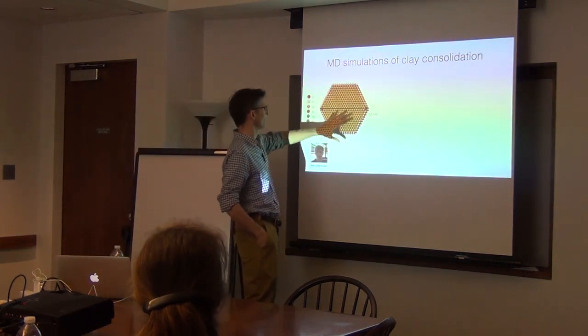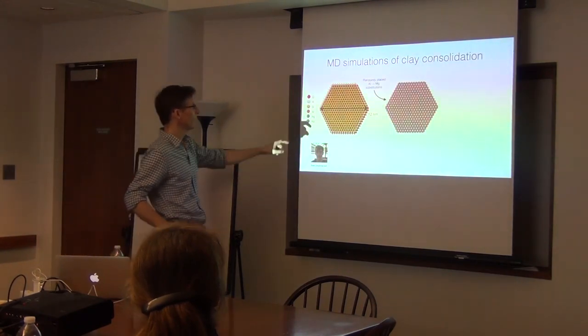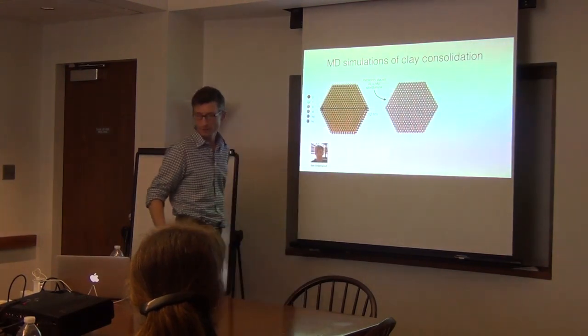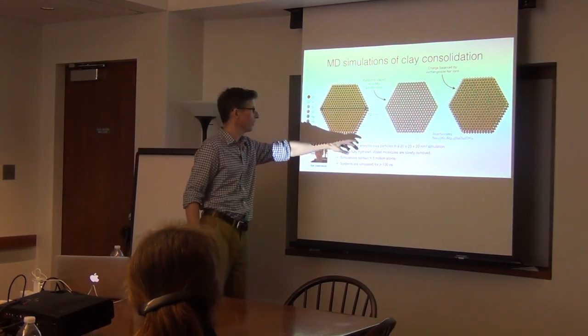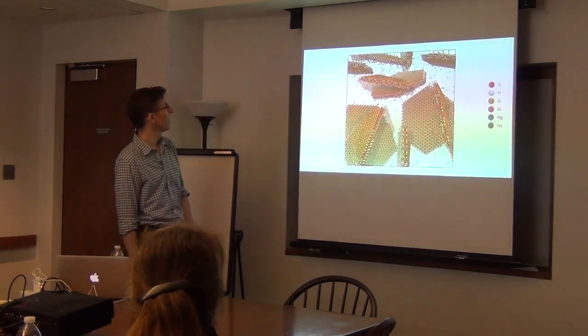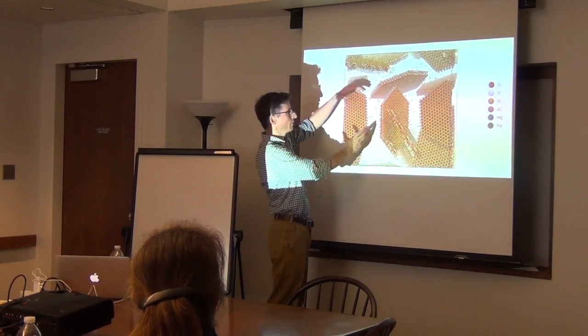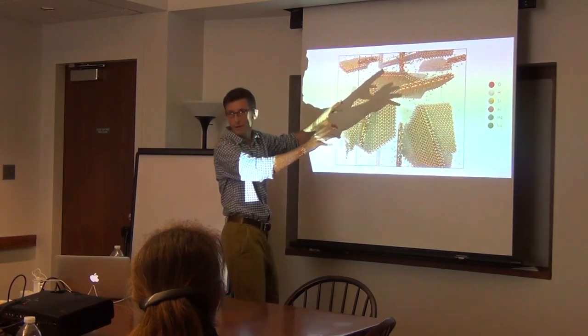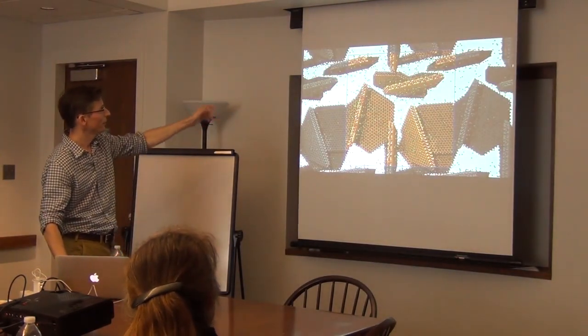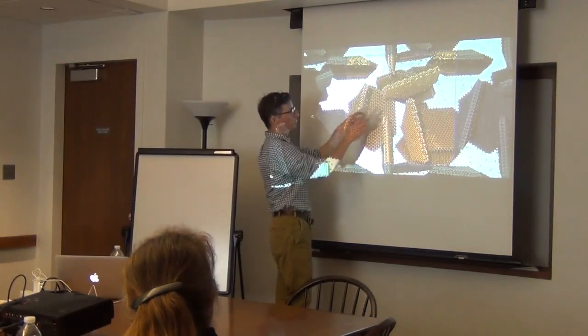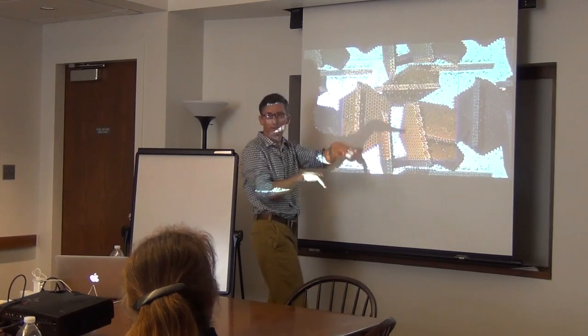Now that we have this, we can model little mini smectite particles — this one is 12 nanometers in diameter, though a real particle would be about 100 nanometers. We randomly distribute isomorphic substitutions to give negative charge, add exchangeable sodium ions on the surface to balance the charge, then place maybe 10 particles in the simulation cell, fill the rest with water, and see what happens. We're slowly removing water and letting the system equilibrate at one atmosphere pressure in the vertical direction, as the particles reorient and stack up and aggregate.